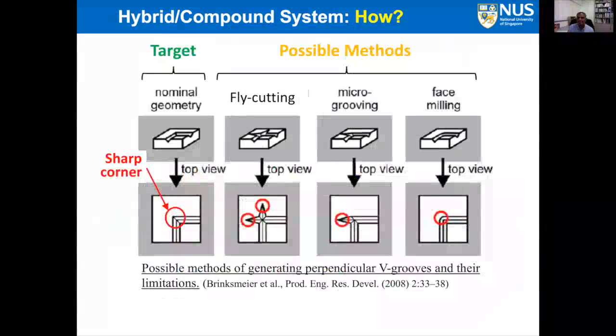So what are the challenges? There are primarily a few challenges. The first one is that in the case of, say, fly cutting, we can produce very good features, but unfortunately, we cannot produce a really sharp corner. As shown in the image here, you will see that there is a small projection that goes on both sides. Under fly cutting, you can see that the surface has some form of the grooves actually extending on either side.